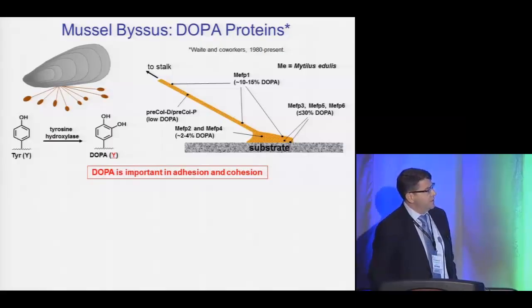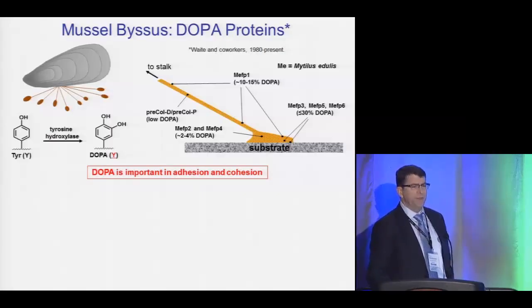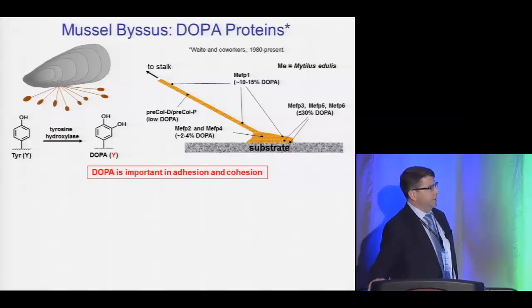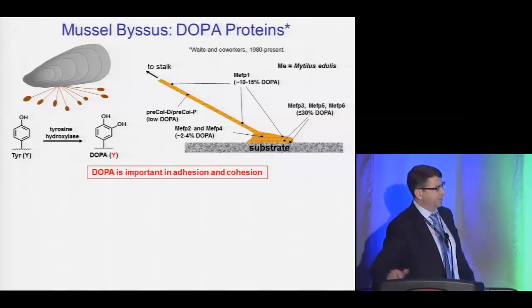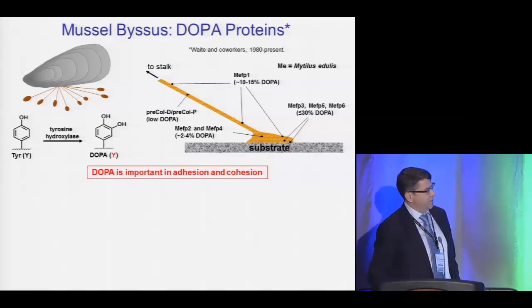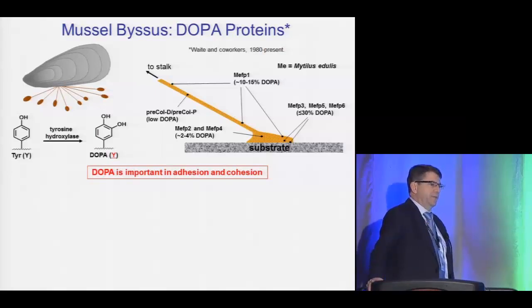And so when we started this work in the late 90s, it was generally recognized that DOPA is important in several aspects of this adhesive structure. One, of course, is adhesion. And this was driven by the observation that the DOPA content is highest at the interface. And also in cohesion. Cohesion, to me, meaning the elastic properties, the bulk properties of this tissue. DOPA is very important. But few of the details surrounding DOPA and its roles were really understood on a molecular level.